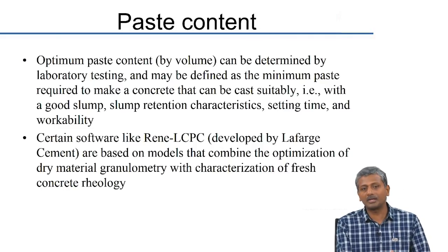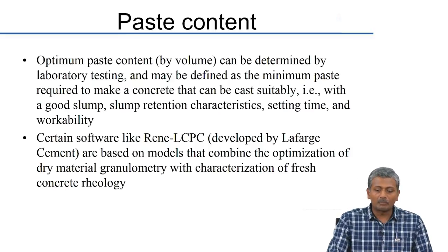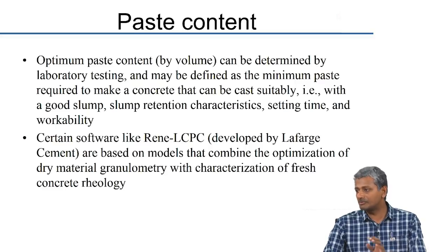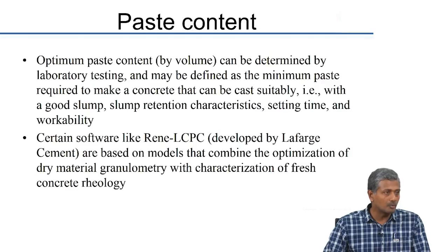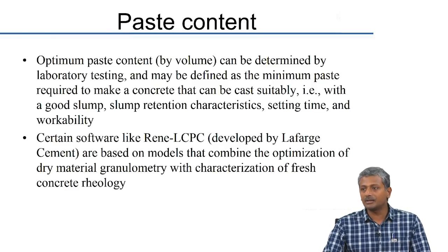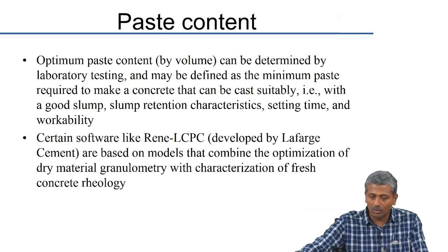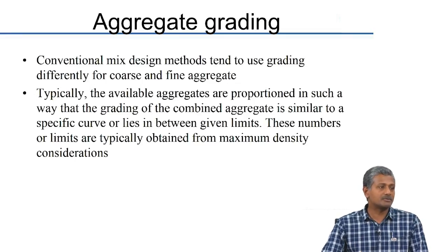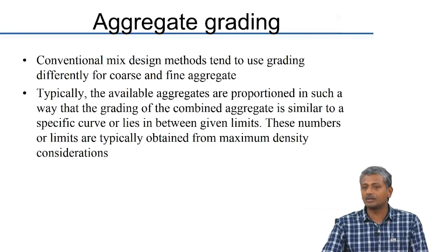One of the basic tenets of modern philosophy of mix design is that you maximize the aggregate composition to obtain minimum void space. Optimum paste content can be determined by laboratory testing and defined as the minimum paste required to make concrete that can be cast suitably. Of course, casting requirements will differ based on the type of application. There are software available which can determine, for a given combination of granular materials, what is the amount of paste required to fill up the void spaces.